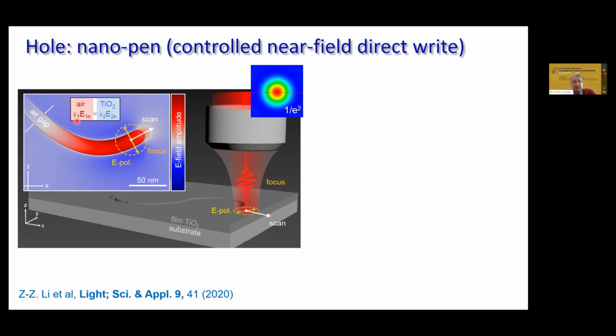And why is it happening? Because it's just a requirement for the normal component of displacement to be continuous at the interface. So permittivity multiplied by electrical field in air should be the same as permittivity of sapphire, in this case, not sapphire but titania, multiplied by electrical field in the film. Intensity is electrical field squared, so the ratio of permittivities squared will be the ratio of refractive indices to the power of 4. So the difference of light concentration here can actually be 20, 40 times.